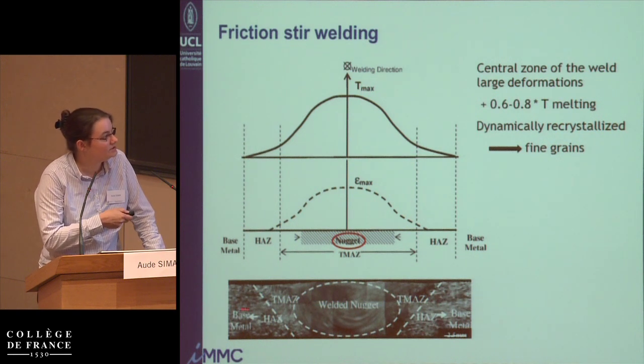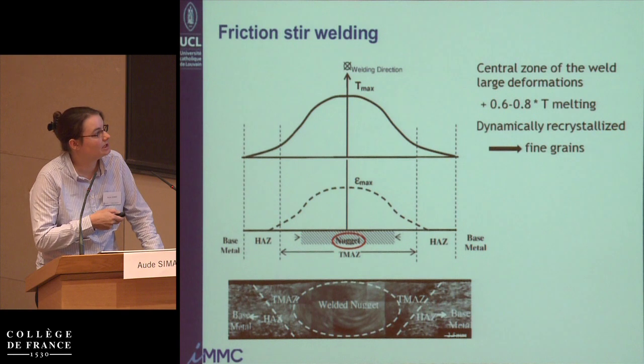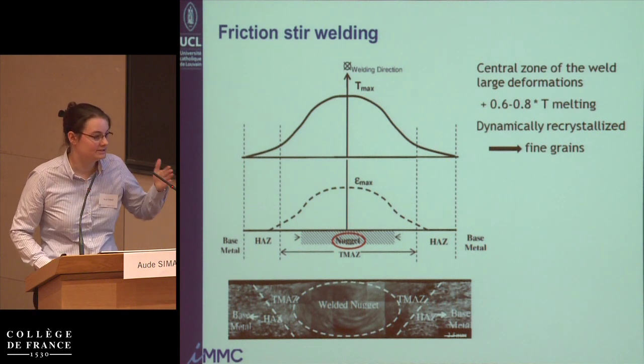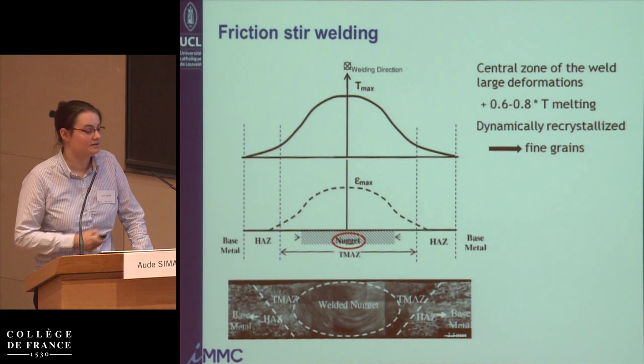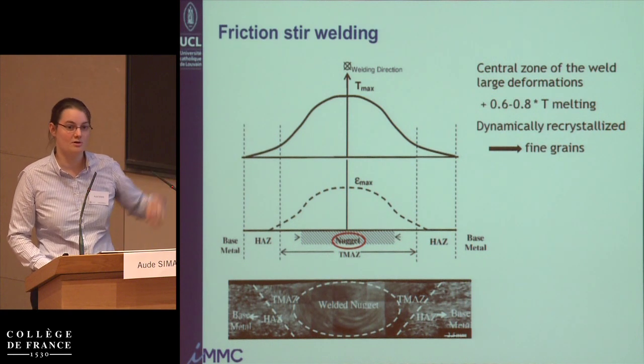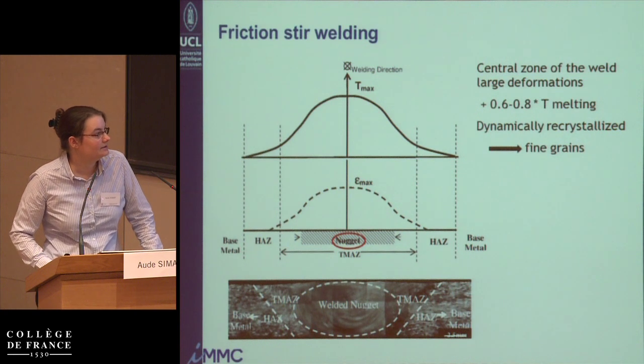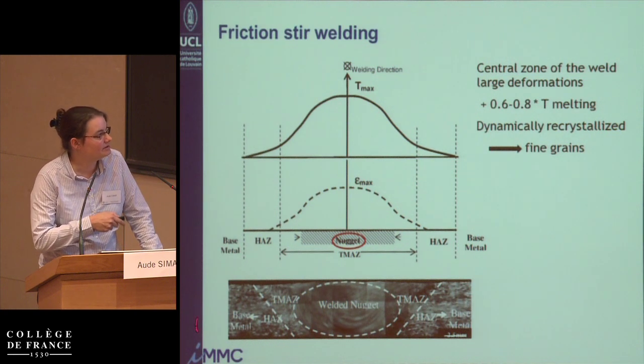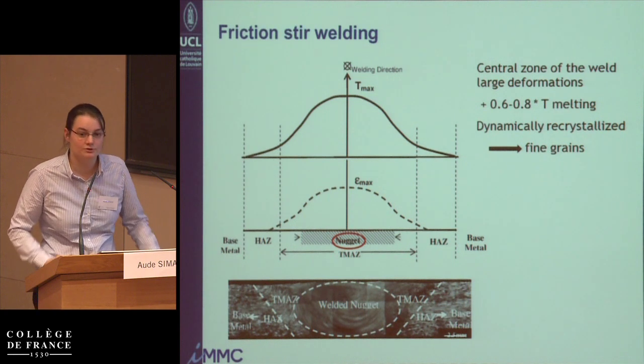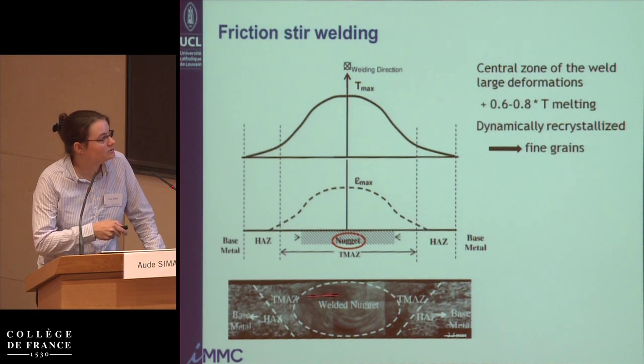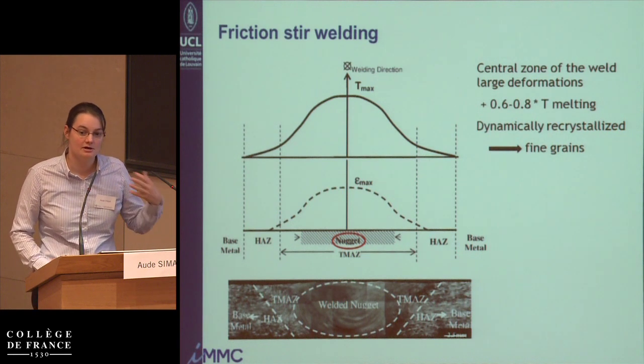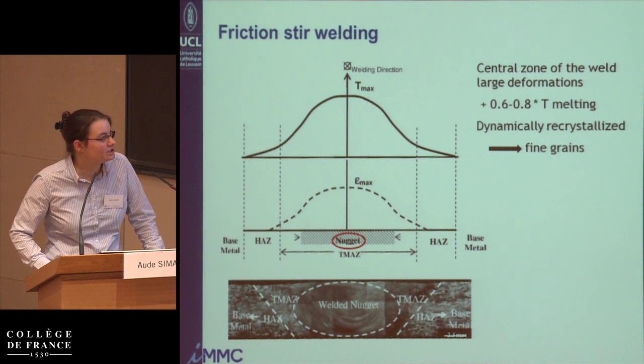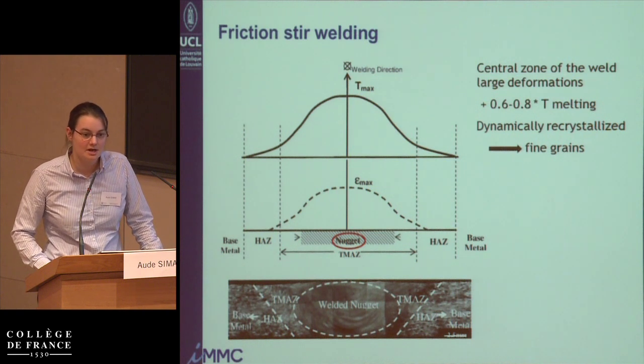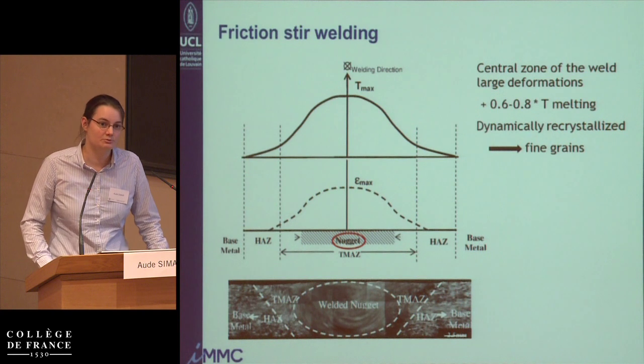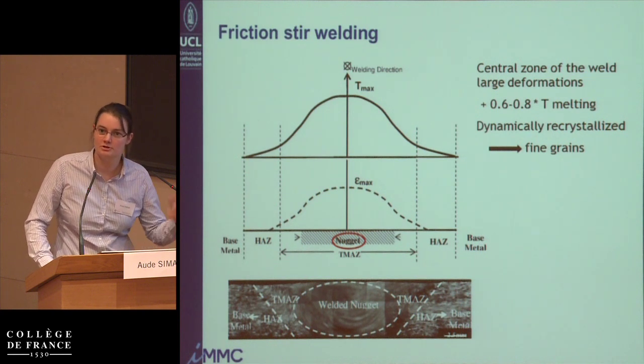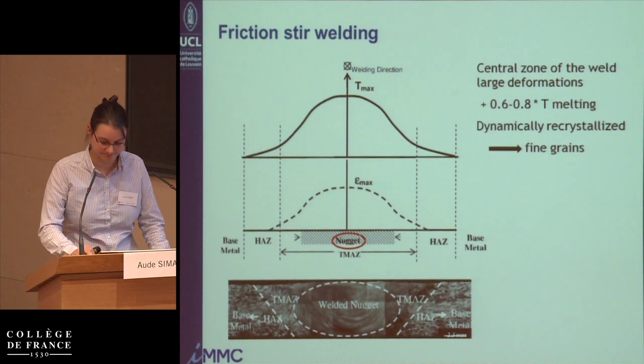So here you see that the base material, so here we are cutting the weld on its side, so the welding direction is coming out of the slide, and so the base material is composed of rather large grains, and when you go in the weld nuggets, you see that you had major plastic deformation and very fine grains. Fine grains are usually associated to very good properties, so it's interesting to look a little more inside this material.